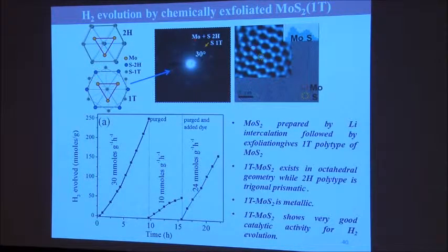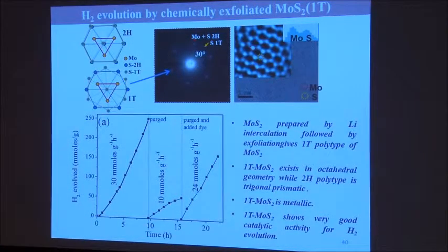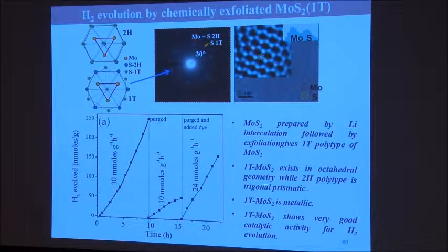But if you do this exfoliation with lithium, you get a 1T polytype. The 1T polytype is highly conducting, it is metallic—unlike the 2H polytype, which is an indirect band gap semiconductor. This is the electron microscopy of the 1T polytype we made in the lab. The 1T polytype exists in octahedral geometry, while the 2H polytype is trigonal prismatic.